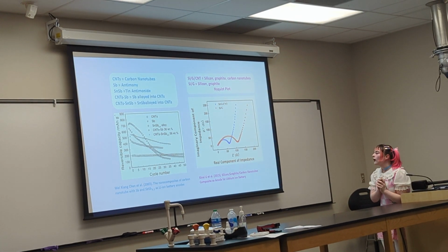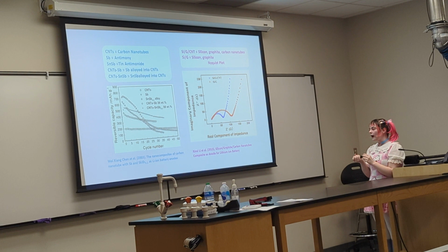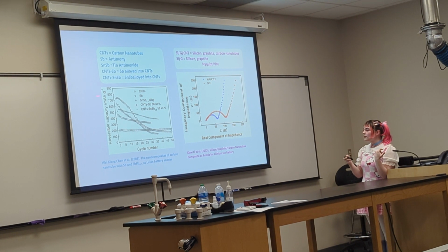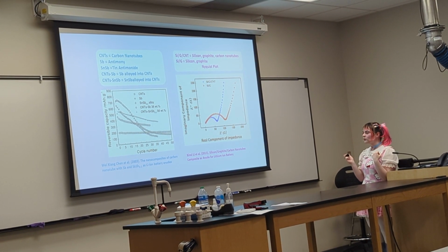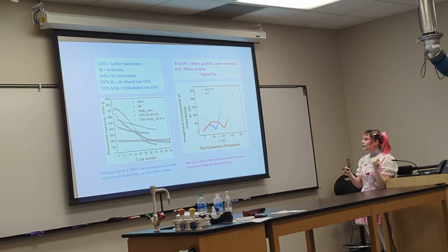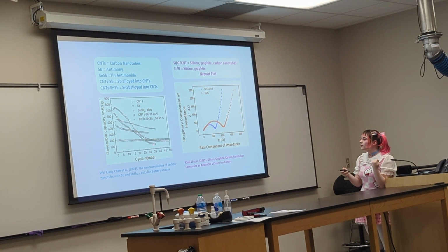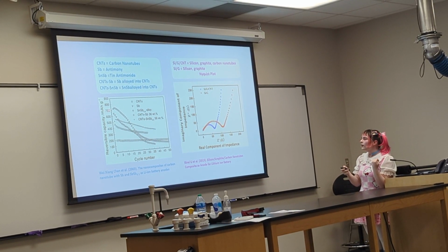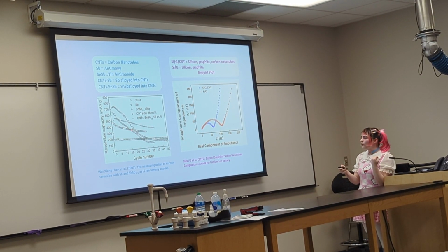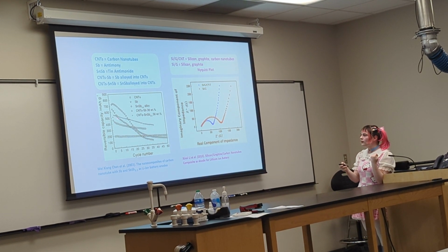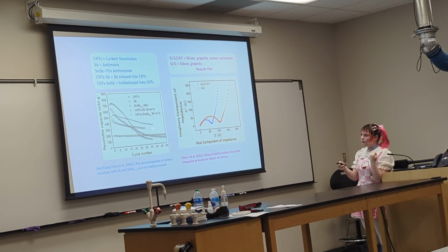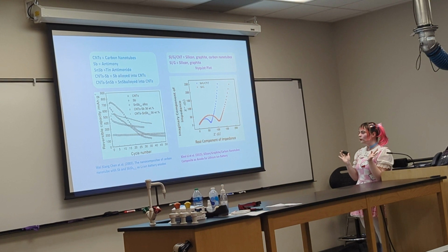So this is some data that goes to show that adding carbon nanotubes into the anode does actually improve its stats. This is the reversible capacity, which is its ability to discharge and recharge. And just carbon nanotubes is at the bottom. And then antimony, it starts up high, but it dips really low. And then tin antimonide also dips. And these two, this is antimony with carbon nanotubes alloyed in, and this is tin antimonide with them added. And both of these endured after 30 cycles. They're doing much better than the materials with no carbon nanotubes involved.